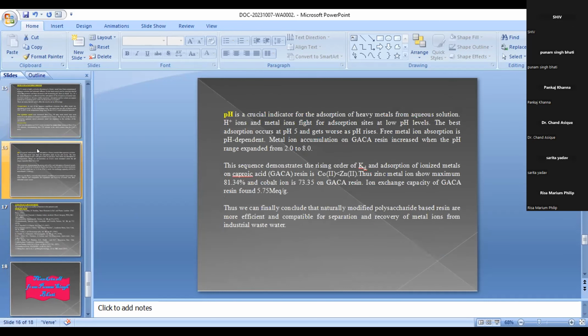The pH is a crucial indicator for the adsorption of heavy metals from aqueous solutions. H+ ions and metal ions compete for the adsorption sites at low pH levels. The best adsorption occurs at pH 5, whereas as pH rises, free metal ion adsorption is pH dependent, and metal ion accumulation on the GCA resins increases when the pH range is expanded from 2 to 8. The sequence demonstrates the rising order of KD and adsorption of the ionized metals on caproic acid resin: cobalt(II) is less than zinc(II). Thus the zinc metal ion shows a maximum of 81.34% and the cobalt ion 73.35% on the GCA resins. The ion exchange capacity of the GCA resins was found to be 5.75 milliequivalents per gram.